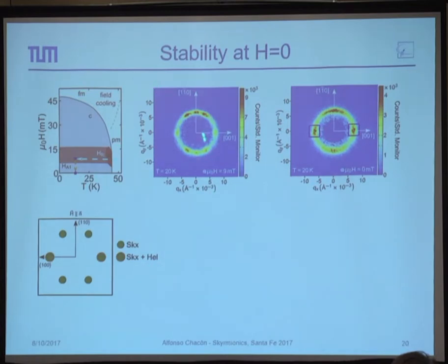So this is the typical Skyrmion pattern that we have at that point. The 6 spots of the Skyrmion lattice, the second somewhat weaker second domain, and if we reduce the field, what you get is this smearing out of the signal. That's probably just the reduction of the signal and the very low angular resolution that we have because of the very long pitch of this system.